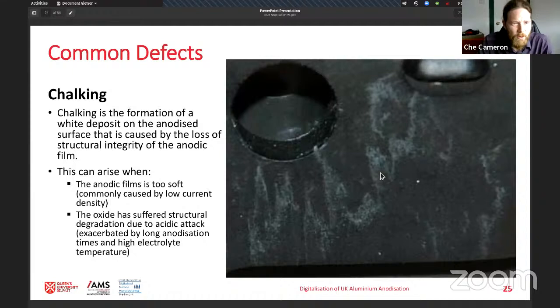And the last defect I'll talk about is chalking. Chalking is a white, powdery deposit that would appear on the surface. And that's basically the loss of that geometric pore structure. It collapses and it forms this powder instead.